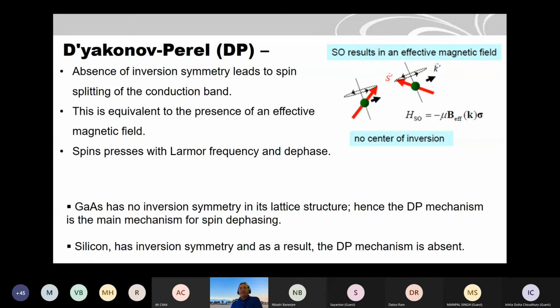So in this case, what can happen is that when electrons are moving in such a crystal, they have the spin orbit Hamiltonian, which depends on the effective magnetic field. And that will differ from place to place when electrons move in the crystal, because the inversion symmetry is broken and you have an electric field, and the electron feels this magnetic field. So that will dephase the spin polarization, and that is called the D'yakonov-Perel mechanism. And this is quite active in materials such as gallium arsenide.